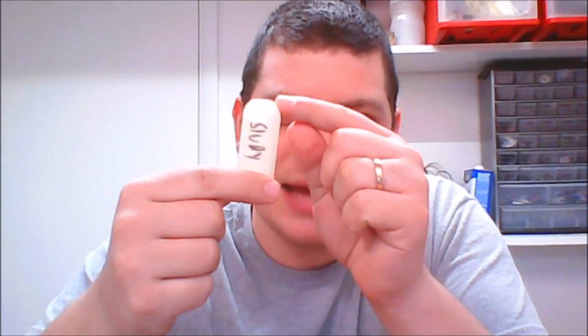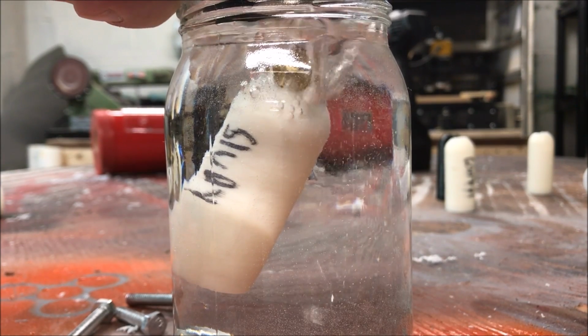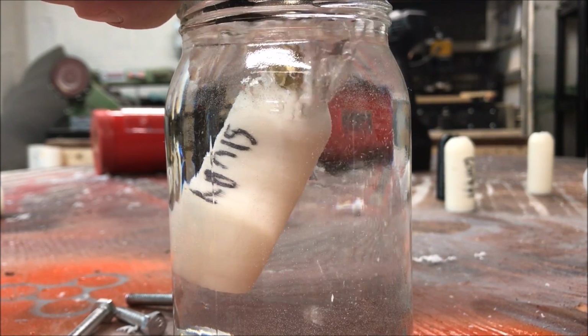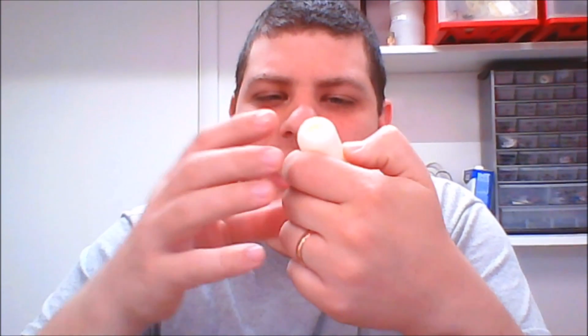The tank that I smoothed with the ABS slurry only leaked from the top, like 10%. Now, I'm pretty sure that doesn't actually have anything to do with the effects of the slurry. I think that has to do with user error. My guess is when I poured in the slurry and sloshed it around, I just don't think I got the top. What I probably should have done is poured a bunch in there, covered the top with a piece of plastic or something since it is acetone, and shaken it around better, and then dumped out the excess. But I didn't. However, the bottom part was completely airtight up to like 140 pounds of pressure, which is fantastic.